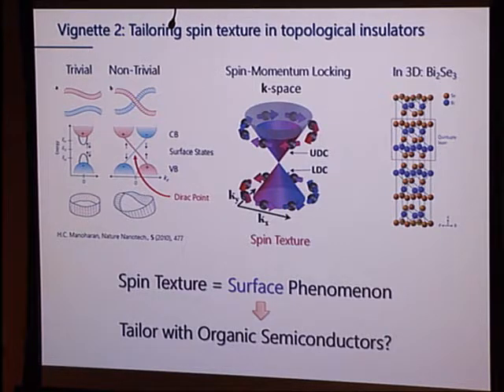They would have to change spin as well, and that's at least in principle forbidden. When you have that, then there must also be a new set of states that appear inside the band gap that connect the same spin symmetries, and these are surface bands that form a Dirac cone, like so. And that leads ultimately to the connection of spin and momentum.